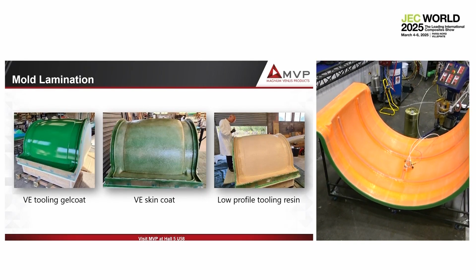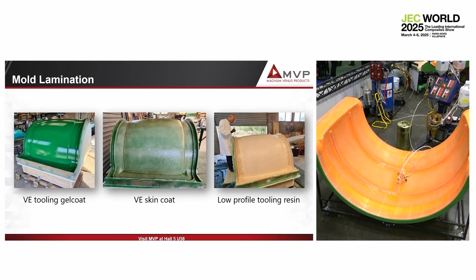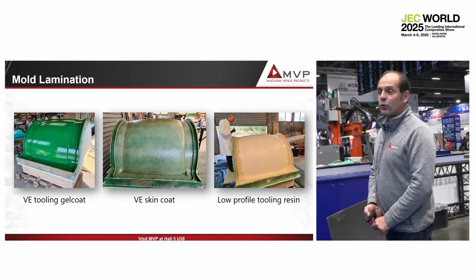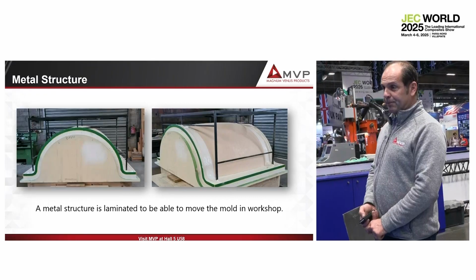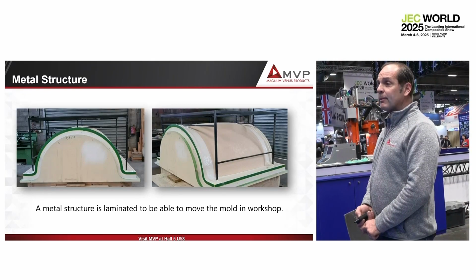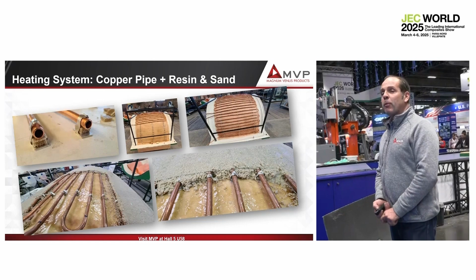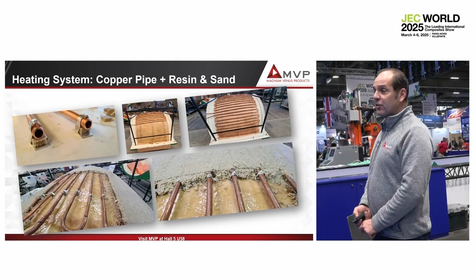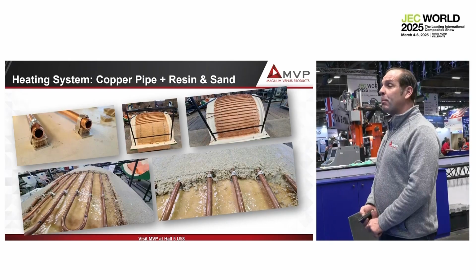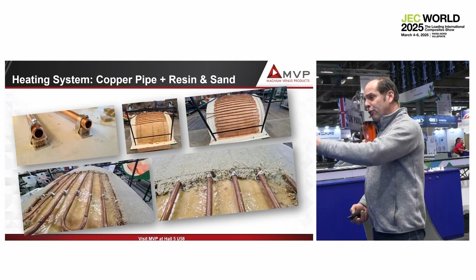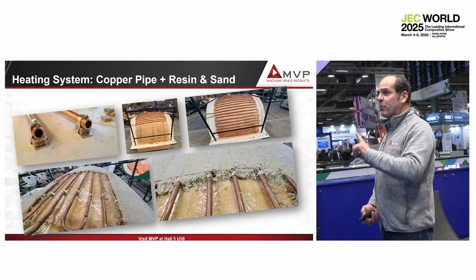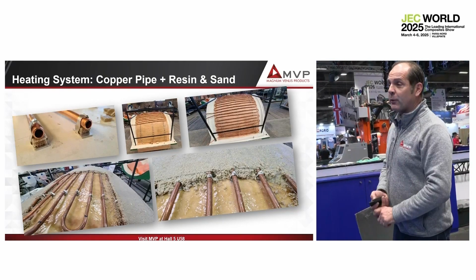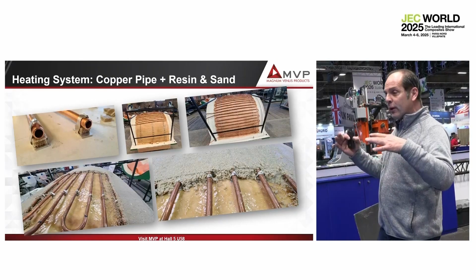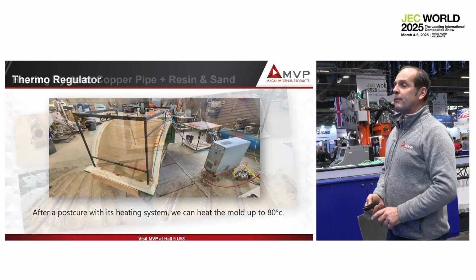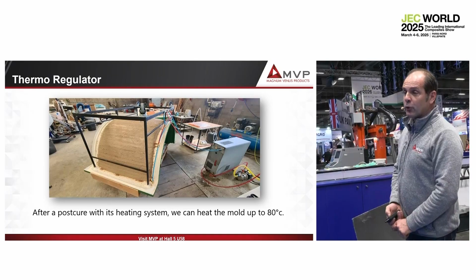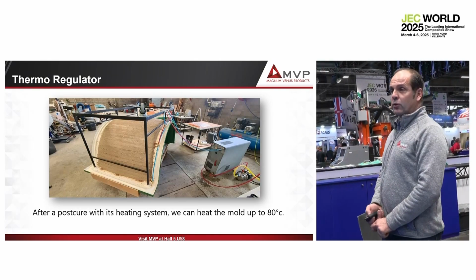So for that, we use a vinyl ester tooling gel coat, a skin coat, and low-profile tooling resin. We use the Euromer resin from the Gazechim group. Then we put the metal structure. And on top of that, we build the heating system, which is a cheap heating system, but helps to regulate perfectly the temperature. On the full surface of 3 square meters, the maximum temperature difference we have is 1 degree. So that's very good. And we use a mix of resin and sand because we have a good transmission of temperature to the copper pipe. So then we also use a heating system, which is a thermoregulator.